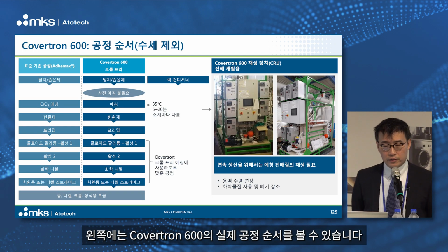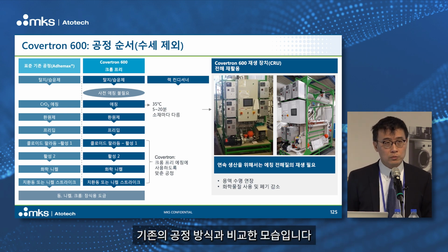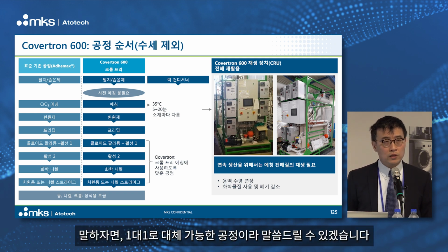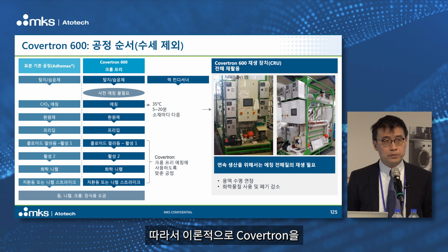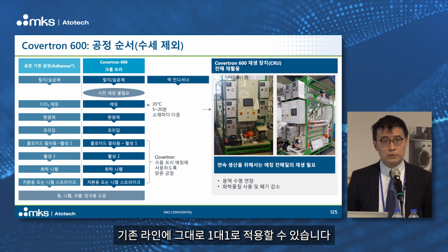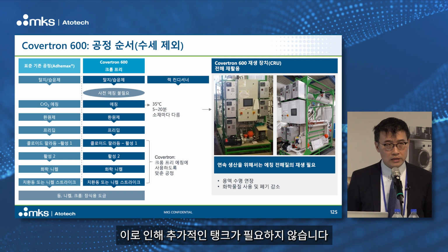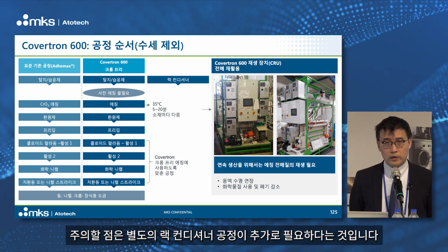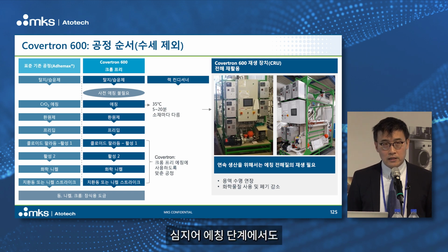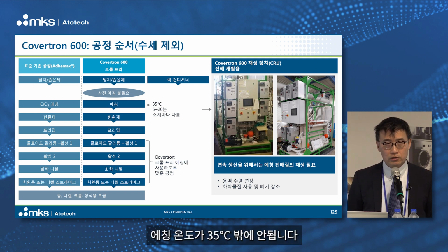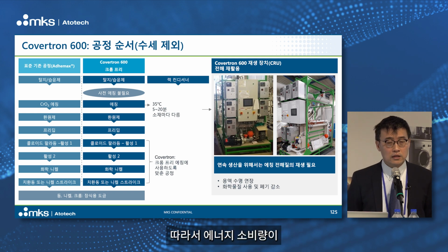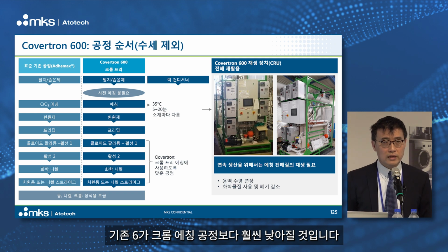On the left-hand side, you can see the real process sequence of Covertron 600 compared to the normal traditional process. I would say it is a one-to-one replacement. So theoretically, you can put in Covertron as a one-to-one replacement for your line, so you don't need extra tanks. The only thing you need to be aware of is that you need an additional rack conditioner process. Other than that, nothing changed. And even for the etching step, the etching temperature is only 35 degrees Celsius, so you can think about the energy consumption being a lot lower than the normal Chrome 6 etching process.